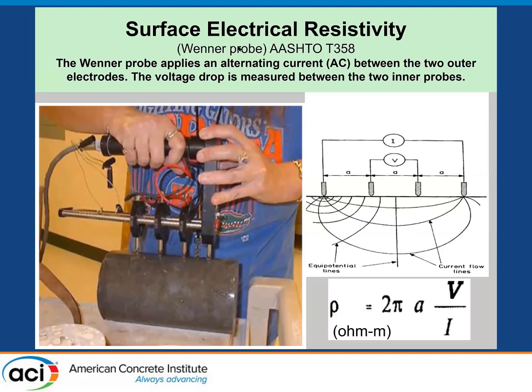Now, the DOTs got excited some time ago about using surface resistivity. I think the real reason they got excited is they thought they could use it in the field, which again is fraught with difficulties. There are 4 probes, it's a surface measurement, and you apply an alternating current over the outer 2 electrodes, which sets up a flow net of equipotential lines. You measure the voltage drop over the middle 2, and you can calculate the resistivity, again, from the voltage and the current and the area of the core of the cylinder. And you do this a whole bunch of times in AASHTO T 358 and get an average value.